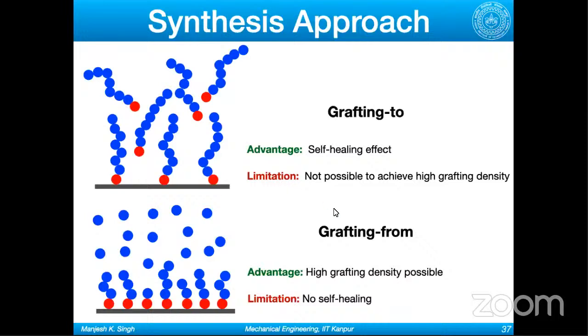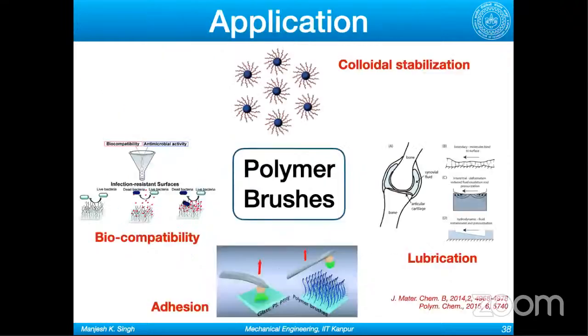But the limitation or disadvantage is that you cannot achieve a very high grafting density here, because suppose these polymer chains are already occupying some spot, then they will not let other polymer chains enter in between. And the other approach is grafting from, where you first attach the initiator to the surface and then you grow polymer chains out of it. Here you will get very high grafting density, but you don't have the self-healing effect. So both the approaches have their own advantages.